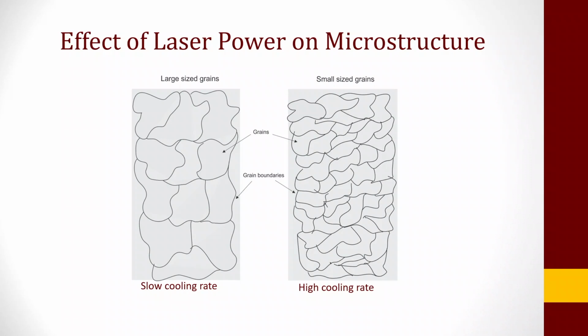Once you have the laser power you select, if you have a slow cooling rate, you could see that you will get large size grains. And if you have a high cooling rate, you would get small size grains. Most of you know that the microstructure will ultimately determine the properties of your material, right? So depending on what type of microstructure you want, you have to choose the laser power in that manner to see if you need a slow cooling rate or a high cooling rate. So you can choose the laser power accordingly.